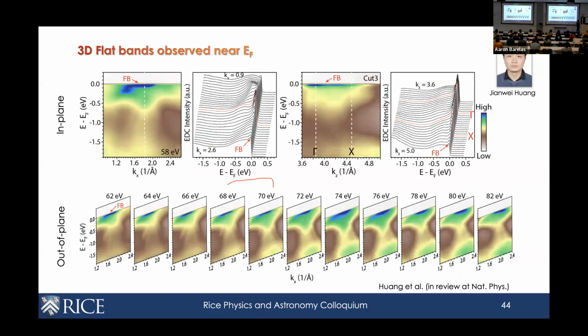So we went through and did these measurements, and this was done by Jian Wei, a postdoc in our group. He really carefully went through a lot of materials to find the best condition to do these measurements. If you look at this picture, blue is the highest intensity, which means you have a very, very flat state across momentum space. You can see that in the peak here, both in the in-plane direction and also in the out-of-plane direction. So this is very consistent with having a flat band at the Fermi level.